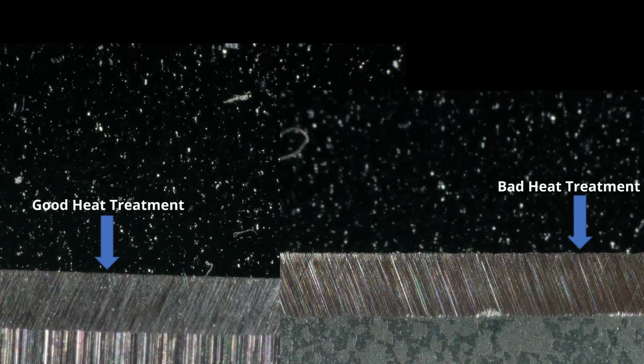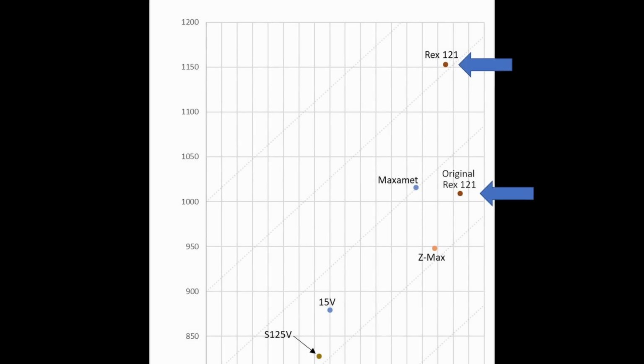So we can't just use something that is necessarily starting duller. Yeah, that affects the whole rest of the test, obviously. If it starts out dull, then the edge retention is not going to be as good. Now, we were able to get really high edge retention with that steel, even though the sharpness was not getting up there as well, just because the steel was so wear resistant.